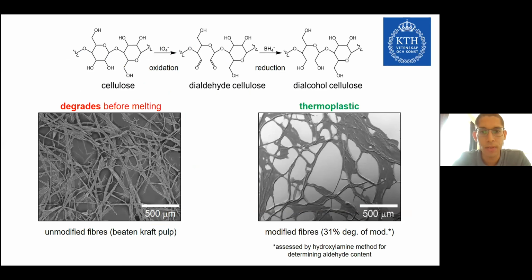So we have identified dialcohol cellulose fibers as a potential replacement or application for extrusion and injection molding. They're prepared by a simple two-step process of periodate oxidation to convert the C2 and C3 hydroxyls to aldehyde groups, followed by borohydride reduction to prepare the dialcohol cellulose. In the SEM images, you can see the unmodified fibers, which degrade before they melt, as we know. And on the right, you have the modified fibers, converted to 31% degree of modification dialcohol cellulose, which is softer and less crystalline. And this behaves in a thermoplastic manner.